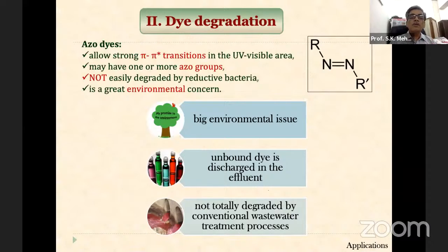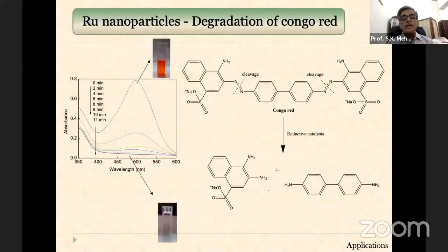So, microwave synthesis of ruthenium that we use for dye degradation. And here we use this Congo red dye, and we found that we can degrade this dye, simply by measurement of the UV visible. You can see initially you have a very prominent peak. With time, the peak disappears, and the color also changes. The color is now colorless.